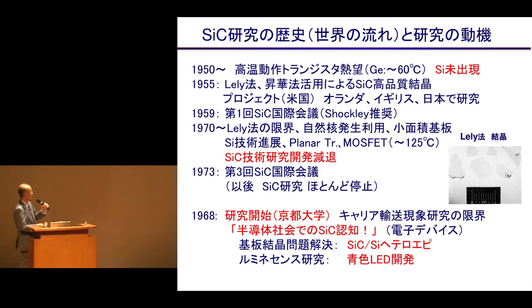So the Lely method was not enough for a device, and also the transistor was made available from the latter half of the 70s, and for IC, and also the operating temperature could be elevated to 125 degrees. So there was a big progress from 60 degrees to 125 degrees. And so there was much focus or interest in silicon, and silicon carbide was now forgotten. And it's as long as 45 years ago that I was interested in this material.